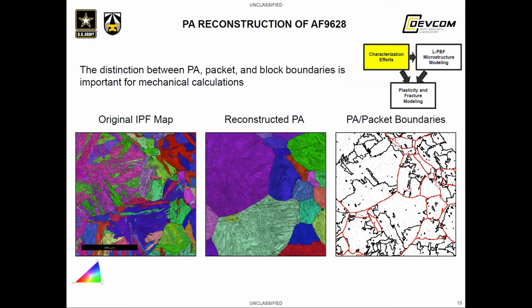So now for some of the useful data that we can get from these reconstructions. Again, looking at the subset of the cast AF9628 sample, the original IPF map on the left with the reconstructed prior austenite grains shown in the middle. On the right is a depiction of the differentiation between prior austenite boundaries in red and packet boundaries in black. The distinction of these boundaries is an important one since packet boundary misorientations are restricted to a possible set of misorientations due to the discrete number of martensite variants that can form from a single austenite grain. The set of austenite boundaries, however, those misorientations are a function of the austenite texture.